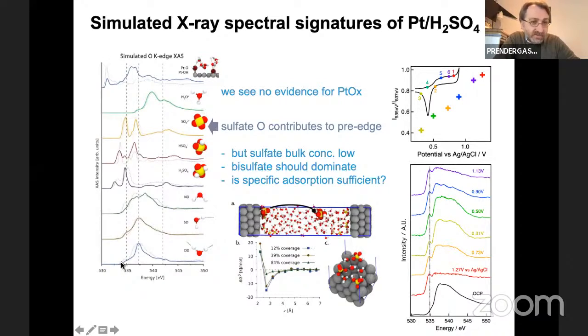Okay, so when we look at all of these spectra and we do the calculations for them, what we find when we do the electrodynamics averaging is that the key contributor at this energy, 535 eV, is the sulfate anion. Okay, now, that was surprising. It's the only candidate that really contributes here. But the bulk sulfate concentration we know should be low. Bisulfate should be the one that's dominating the spectrum. And then maybe if there was specific adsorption of this dianion to the surface, maybe that might enhance its population, but we weren't sure if that would be sufficient.